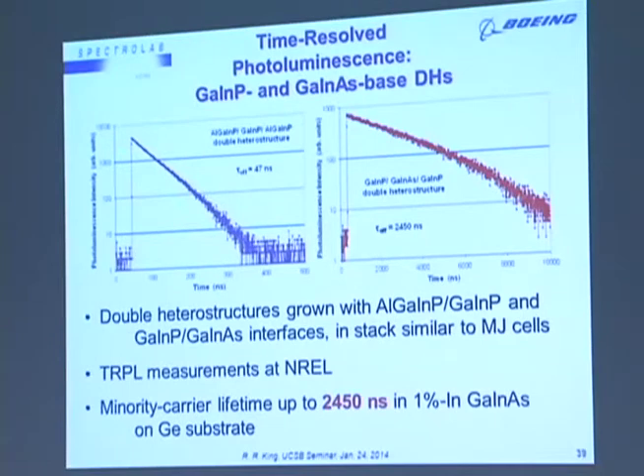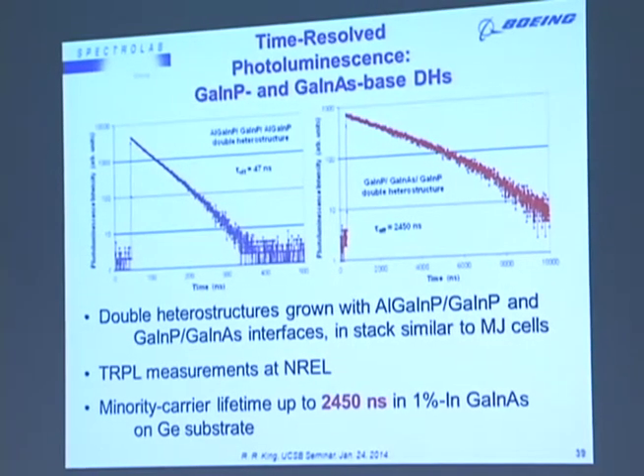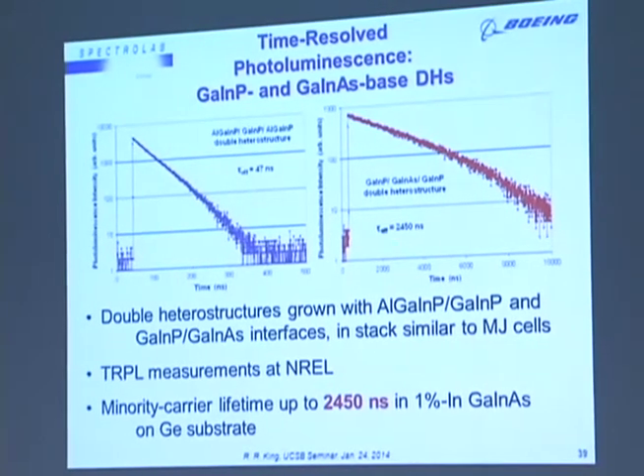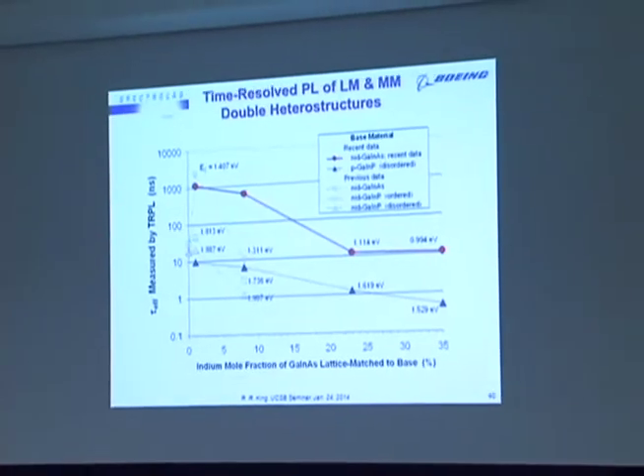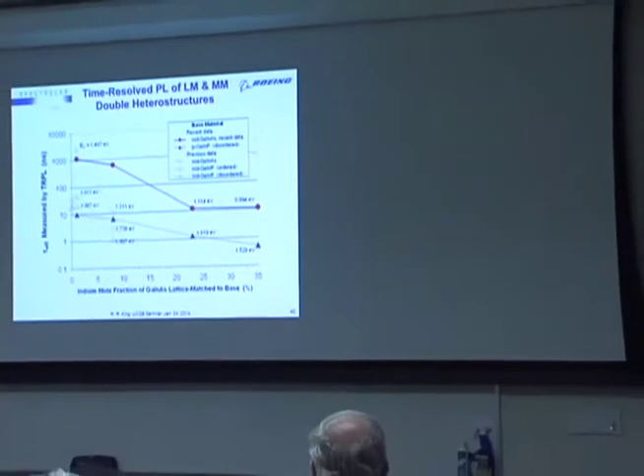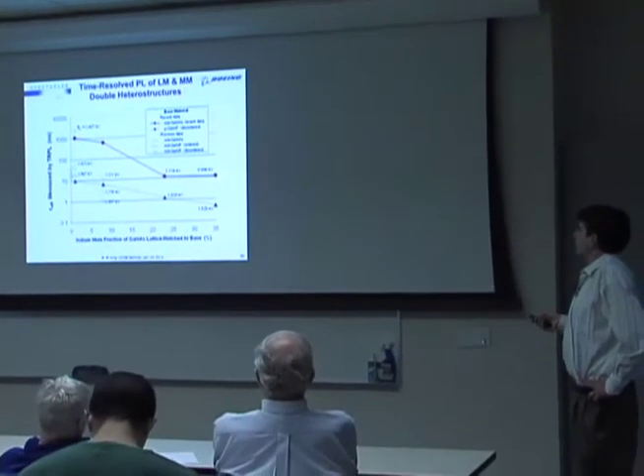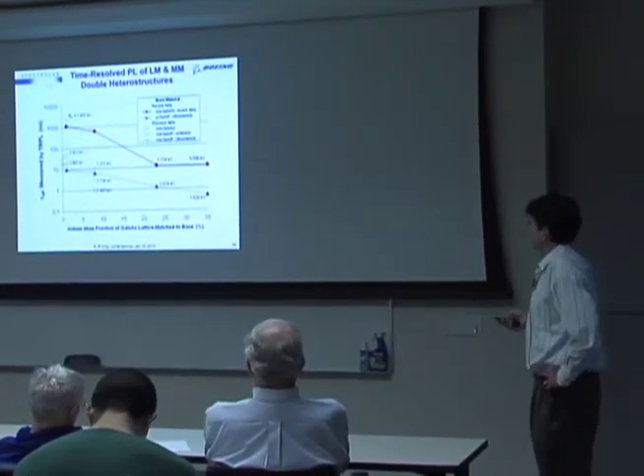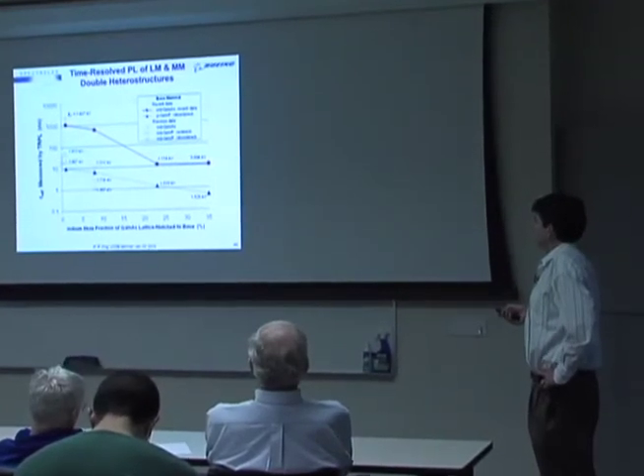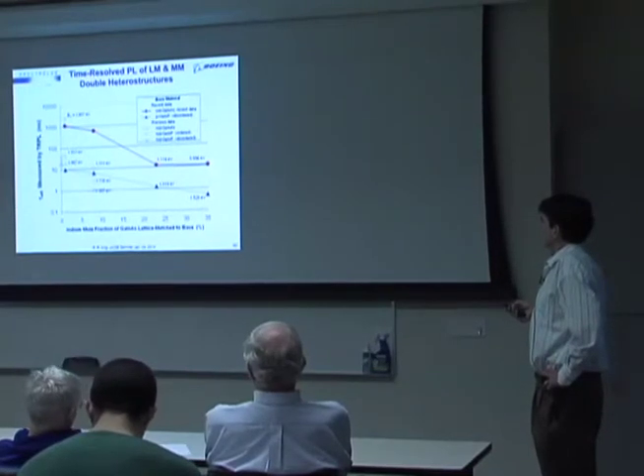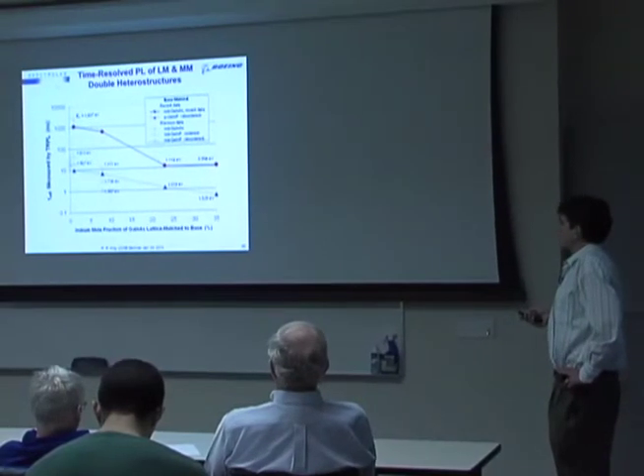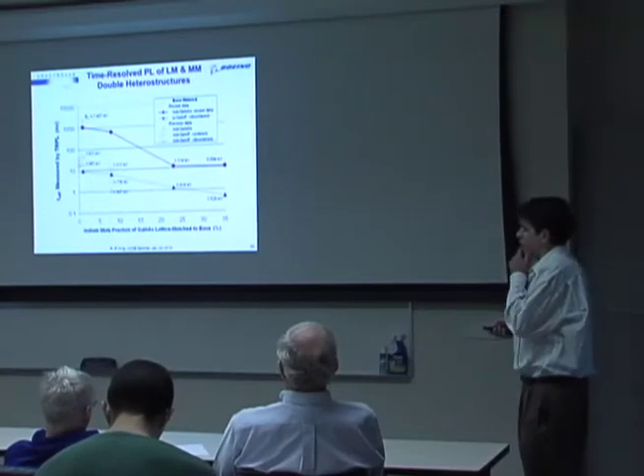These are some time-resolved photoluminescence curves in gallium indium phosphide and gallium indium arsenide. So these were time-resolved photoluminescence measurements done on double heterostructures grown at Spectrolab, and the TRPL measurements were done at the National Renewable Energy Laboratory. So we can see minority carrier lifetimes up to over 2 microseconds in these materials, which is quite long for a direct bandgap semiconductor. This just shows the way that the minority carrier lifetime drops off with increasing lattice mismatch. Also shown here is the difference in minority carrier lifetime for both ordered gallium indium phosphide and disordered gallium indium phosphide. There seems to be some difference, though not a large difference, in the lifetimes in those ordered and disordered materials.